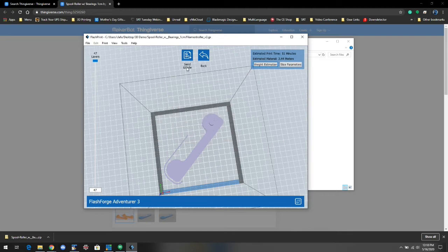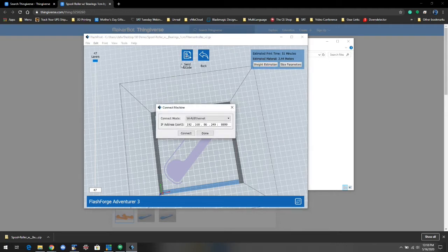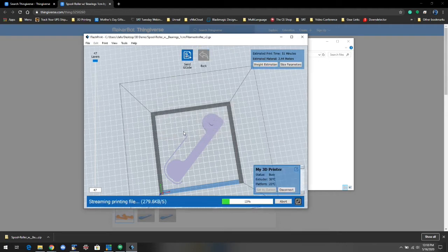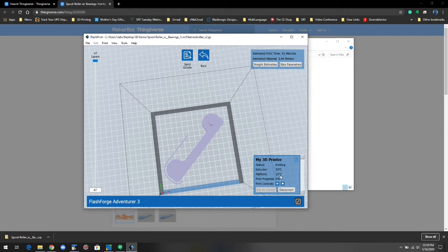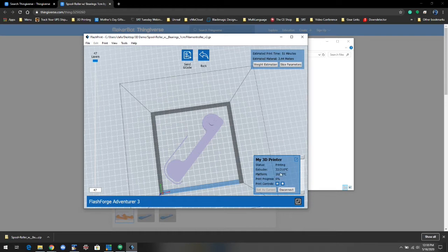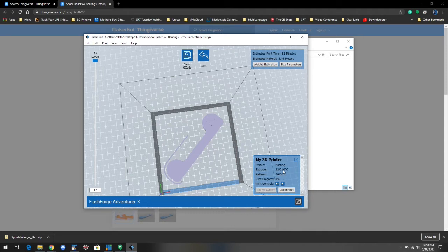Send G-code is what sends it over to the printer. So I'll click that. This is where my printer is on my network. Click Connect. So you can see the temperatures that are here. Everything has to heat up somewhat to be able to get a good print. The printer bed or platform, we have set to go to 50 Celsius. The extruder has to get up to 210 so they can melt the plastic or the filament.